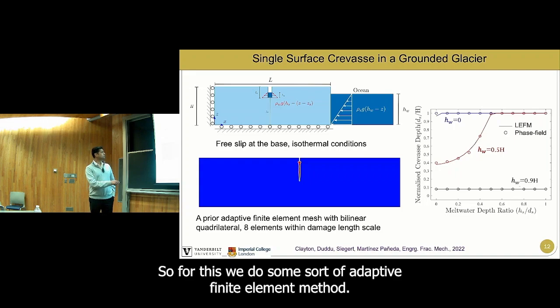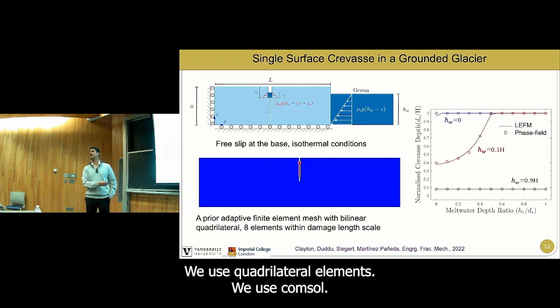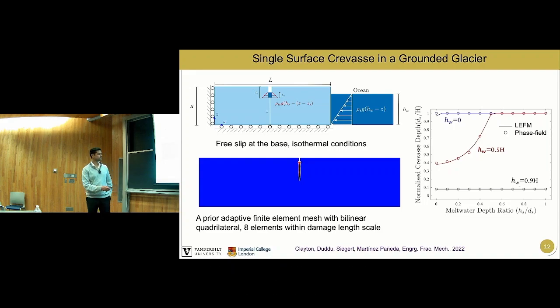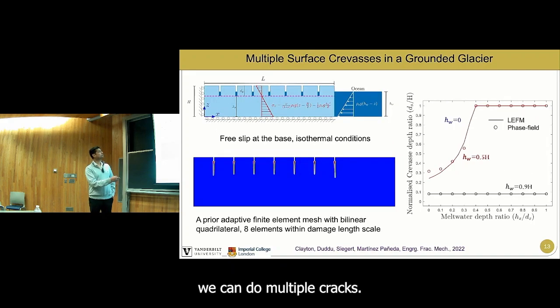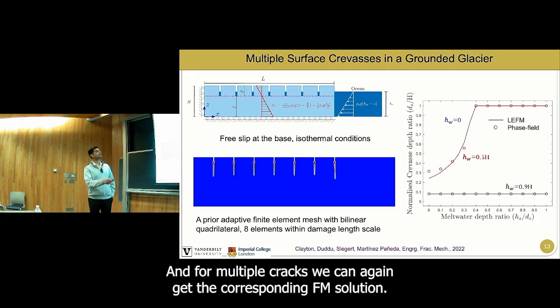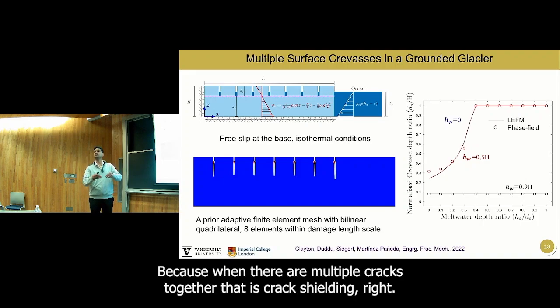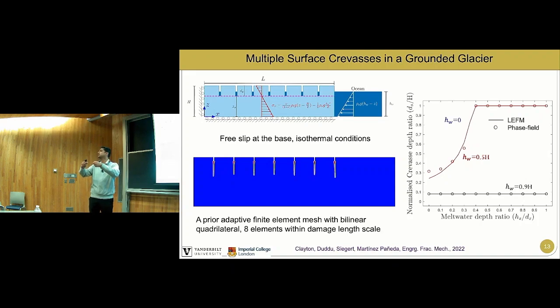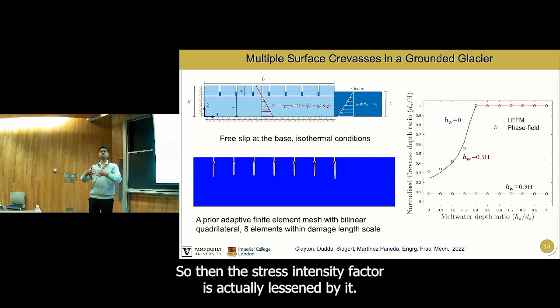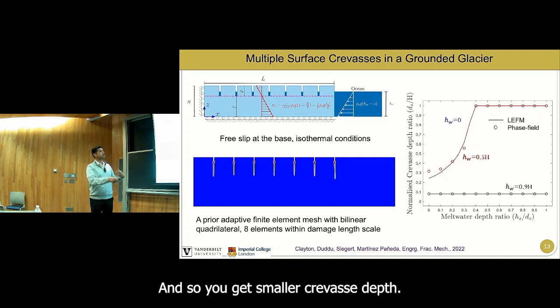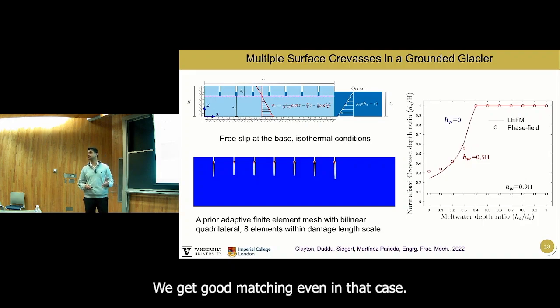So for this, we do some sort of adaptive finite element method. We use quadrilateral elements. We use COMSOL in this case. We can do multiple cracks. And for multiple cracks, we can again get the corresponding LEFM solution, because when there are multiple cracks together, there is crack shielding, right? So then the stress intensity factor is actually lessened by it. And so you get smaller crevasse depths. And then we compare that with phase field, we get good matching even in that case.